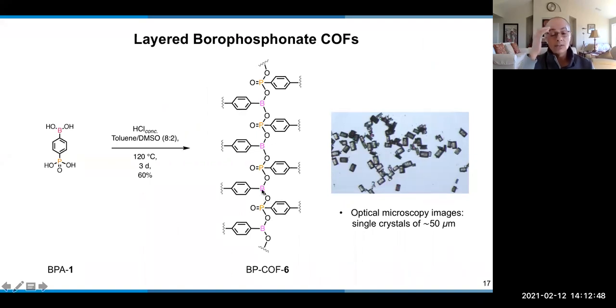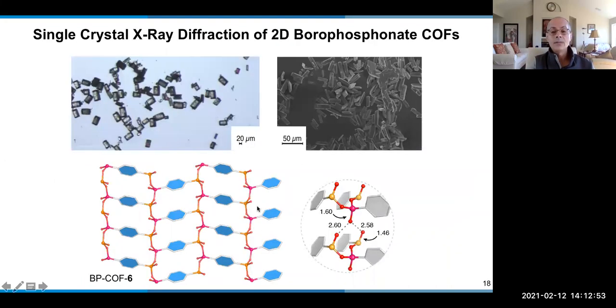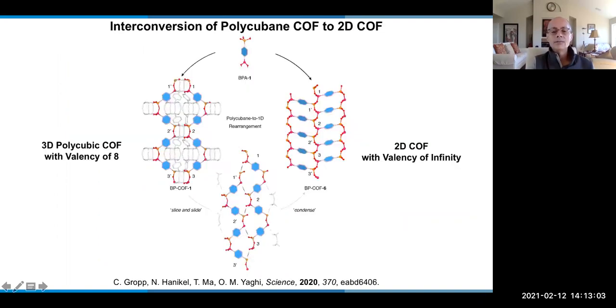This is not a unit that is known in chemistry. But we are able to trap these units in these COFs by virtue of having a water molecule that's sitting on the boron position, linking the layers together. It's a very, very nice way of making these, in that you take the polycubane, when you add acid, you just basically unzip the cubes. You break every cube into 2 parts, okay? And then these parts come together to make the chains.